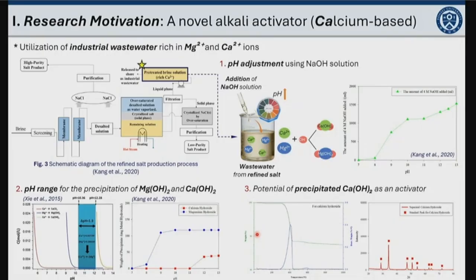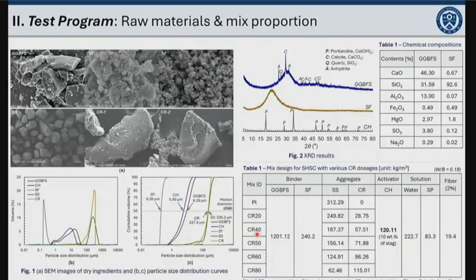So we adopted calcium hydroxide as a new activator for fabricating the cementless strain-hardening slag compound. This is the chemical and geometrical properties of raw materials and mixed proportions. The blast furnace slag was used as the main binder instead of cement, and it is activated by the powder type calcium hydroxide.